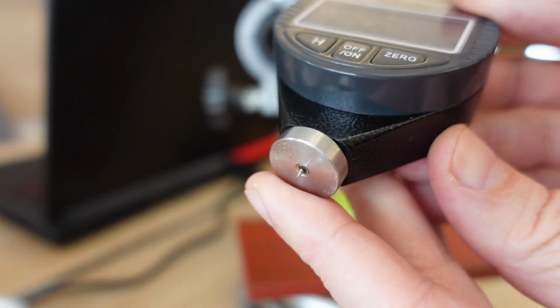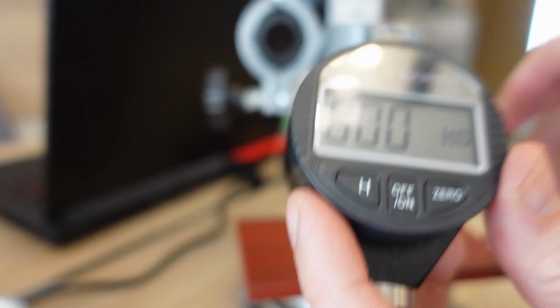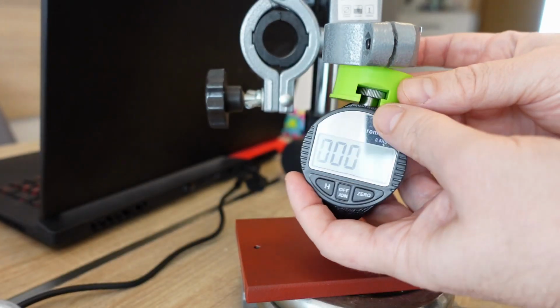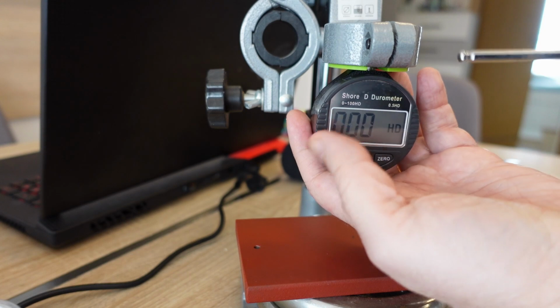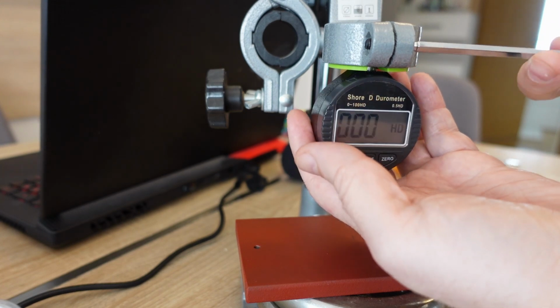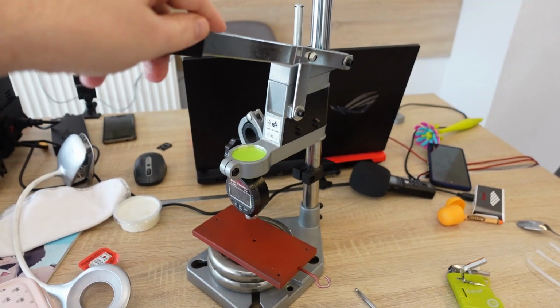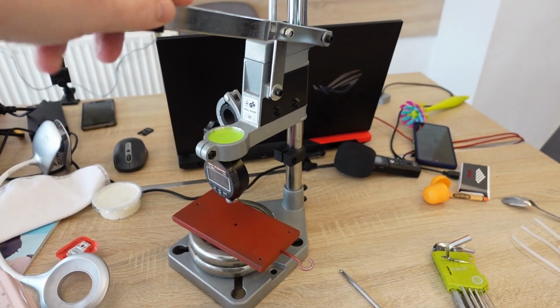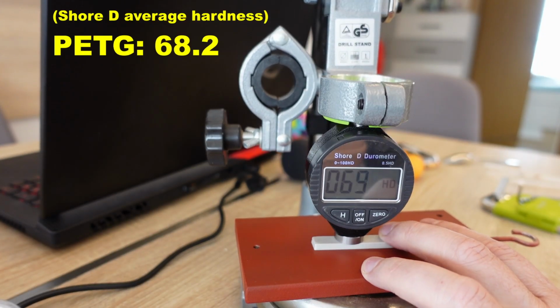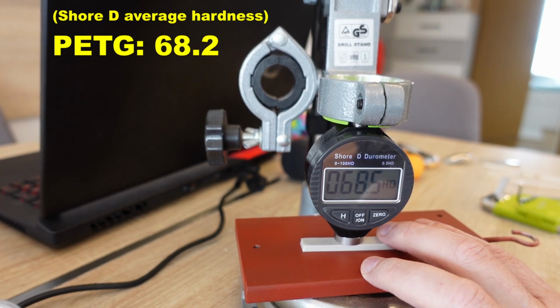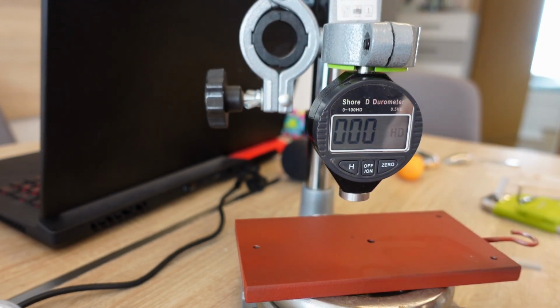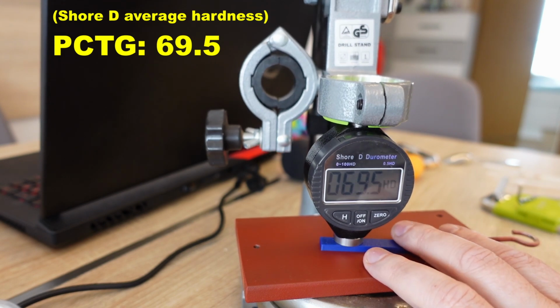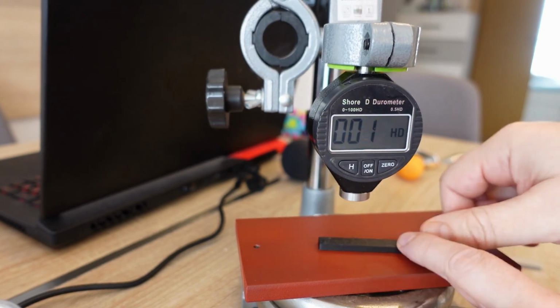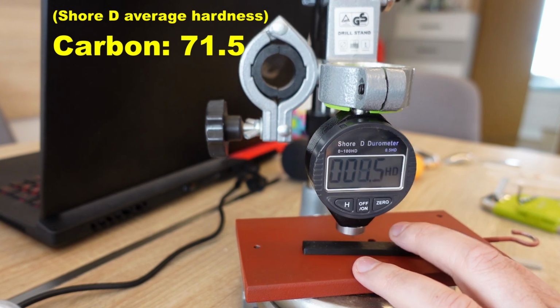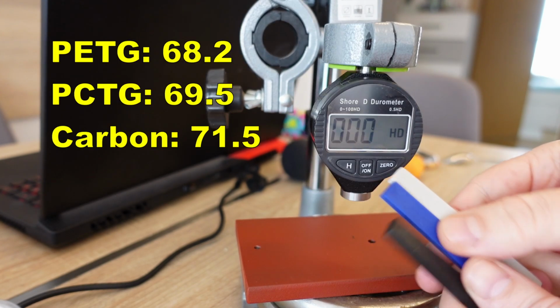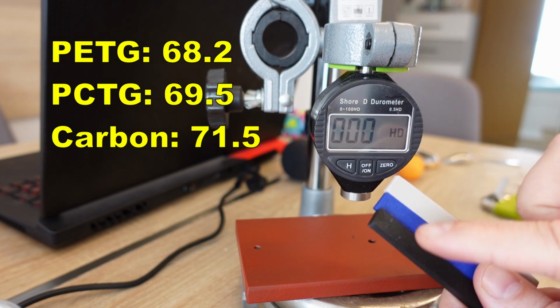So this is a Shore D durometer. It has this sharp needle which will penetrate into the material, and it measures how deep it goes into it. And this is my test equipment. I'm starting with PETG. The average is 68.2. This is PCTG, and yes, it is harder, so theoretically maybe it is more scratch resistant, but the carbon version, probably thanks to those carbon fibers, is even harder.